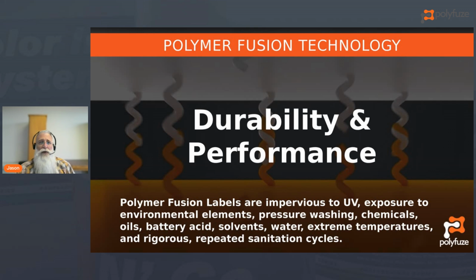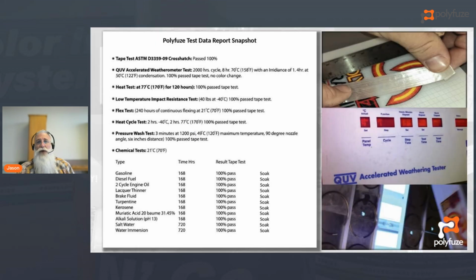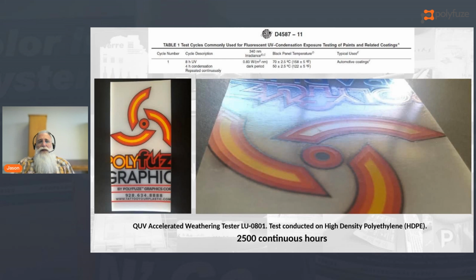So certainly we are known for our durability. And that's one of the number one reasons why people come to us: they're looking for that durability for 10 years, 15 years. This is just a really quick snapshot of our test data report. And when you get down into the chemicals section, those are not mists or wipes. We're actually soaking that label material and the base plastic in those chemicals for hours and hours and hours without any sort of degradation.